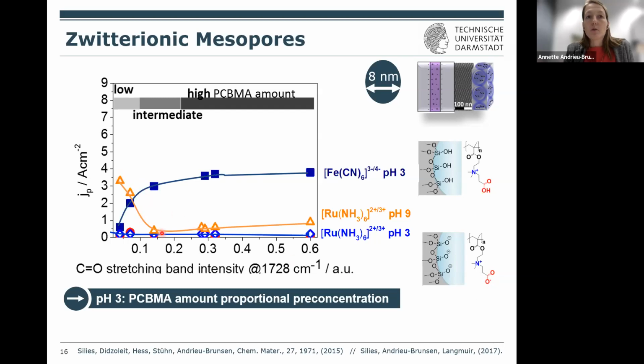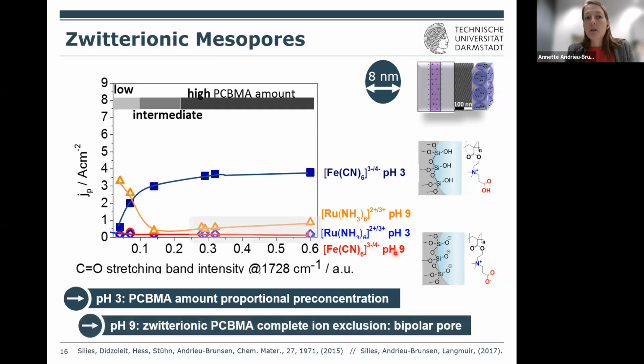You see first the polymer amount influence. But if you have a certain polymer amount, the pore is almost closed for the positively charged molecule, but it's as well closed for the negatively charged one. And this is not what you would expect intuitively. And this is a so-called bipolar pore. So what you see is that if you have zwitterionic polymers in these pores, actually no counter ions, independently of their charge, like to enter these pores anymore.